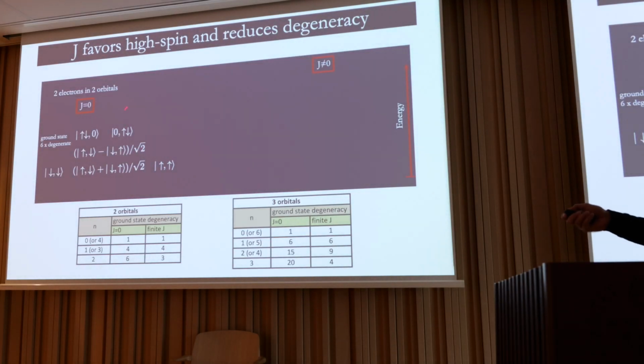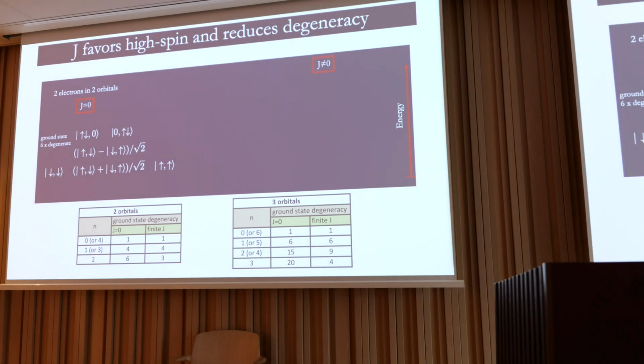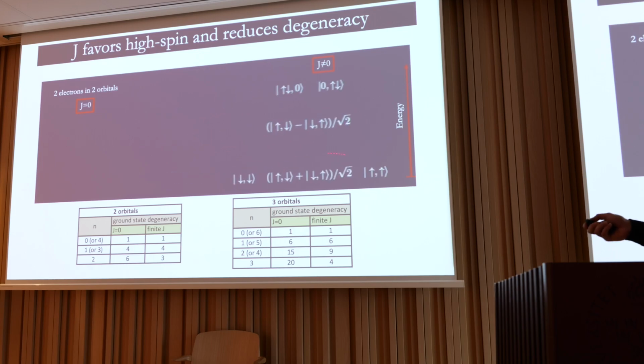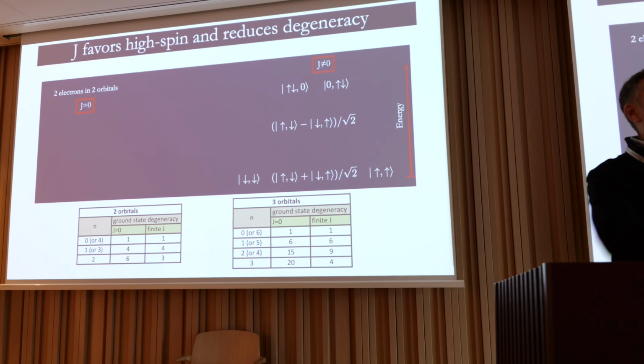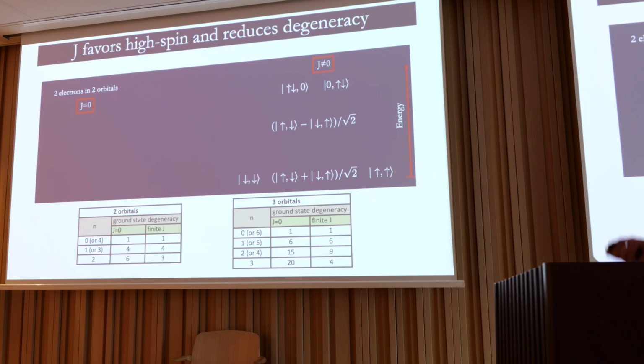If you have two electrons in two orbitals, you have 6 states which are degenerate if you don't put Hund's coupling, and if you put Hund's coupling, you have a multiplet splitting. So you reduce the degeneracy, and these configurations are the ones that you have to use when you hop around the lattice, so you have a constraint that makes your life harder. And this is true also for 3 orbitals.